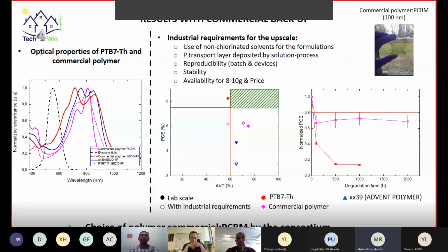Stability is always an important parameter, and as we can see in the graph, the commercial polymer had quite good stability under illumination, because after 2,000 hours, 70% of the initial performance is kept. Nevertheless, with the PTB7-Th, after only 500 hours, 85% of the initial efficiency is lost. So with the consortium, we decided to choose the confidential commercial polymer for the development of the transparent solar cells.